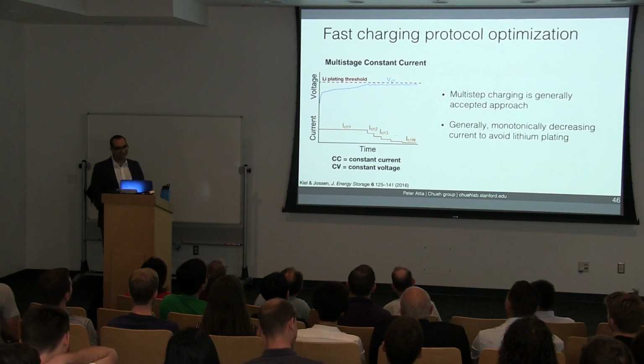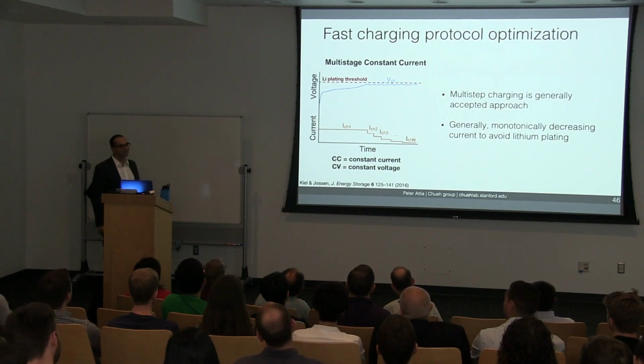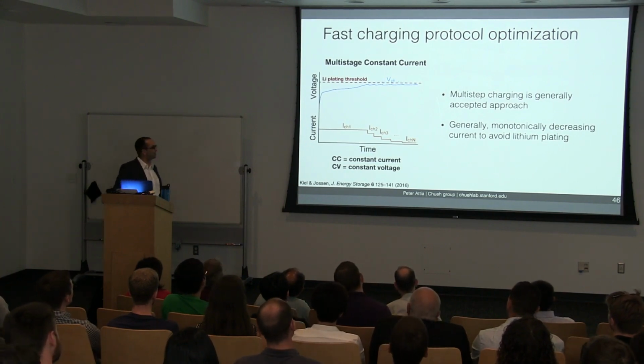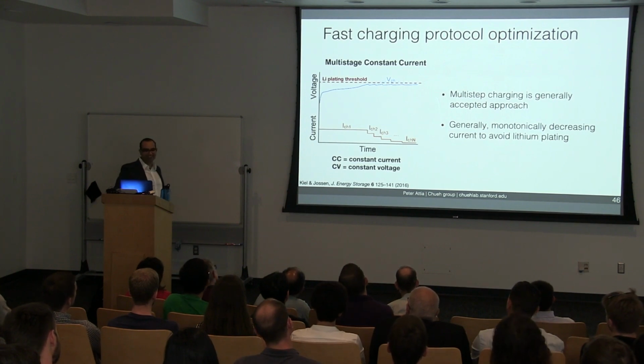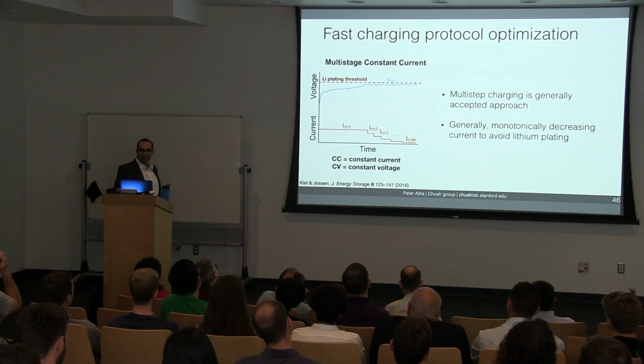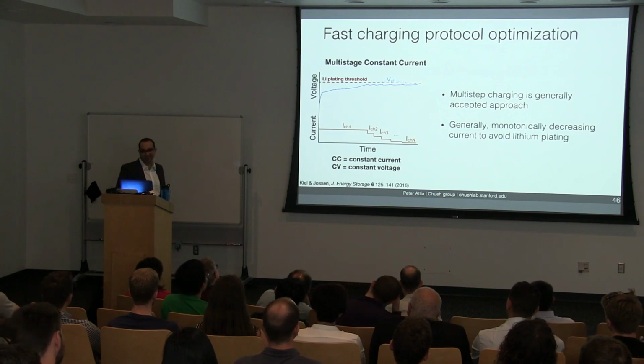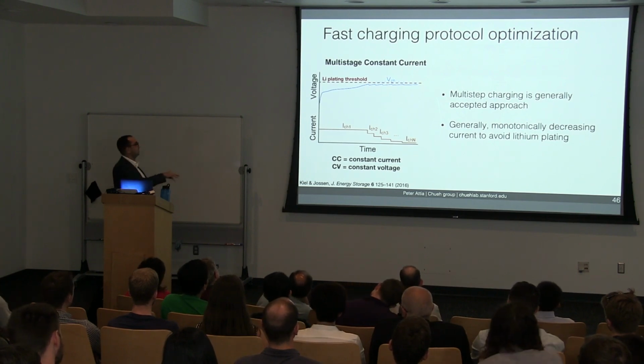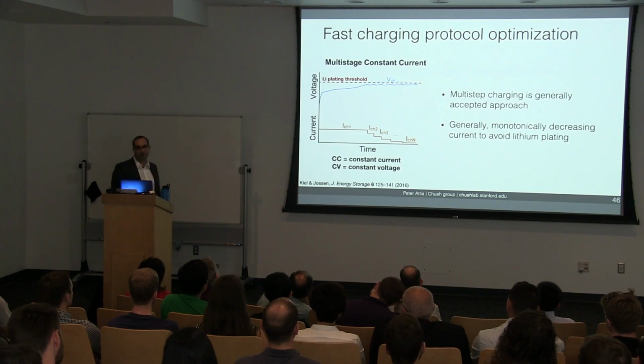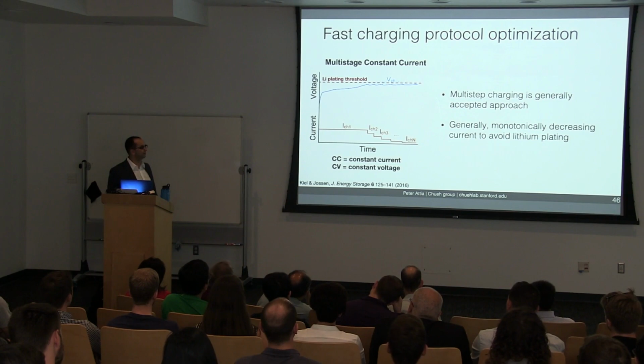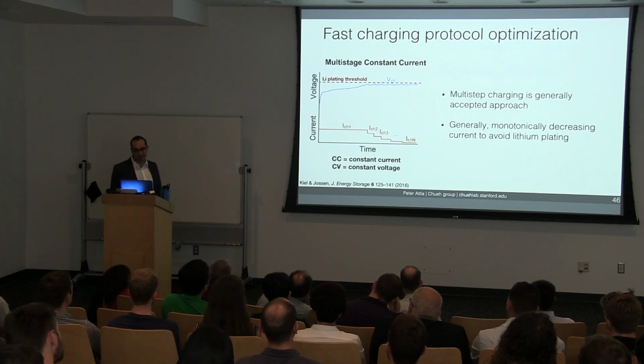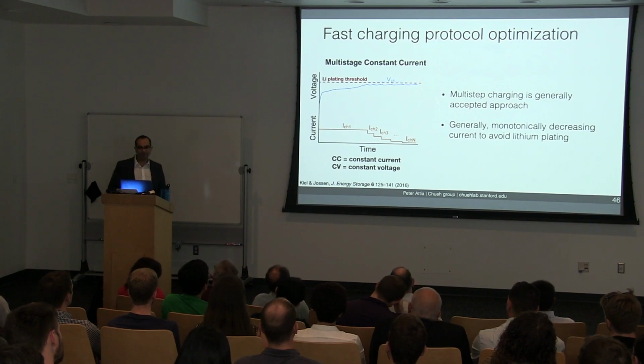Okay, so all jokes aside, there's actually been a lot of previous work on battery degradation. A standard approach is multi-step charging. The idea is that different degradation modes manifest more prominently at different states of charge. So most of the previous literature suggests that the current steps should be monotonically decreasing to avoid the lithium plating potential threshold at high potential. Lithium plating is a canonical degradation mode during fast charging. Now, of course, the challenge here is determining the right values and locations to use for these various current steps. The number of possibilities blows up really quickly.